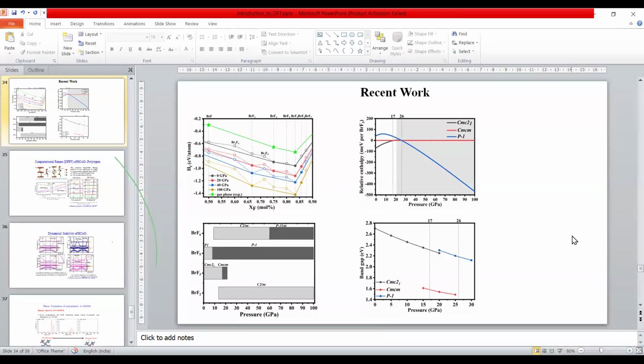If you are using LDA, you find some minus 10 electron volt minimum energy. If you are using GGA, you find minus 12. Then you have to find out which will give you the minimum energy, and a good lattice constant which matches the experimental value. For example, you are talking about MoS2, so you have to find a very good experimental paper which will give you the lattice constant value. Then you compare with your optimized system using LDA, GGA, LDA plus U, GGA plus U, whatever you use. Then you can decide which pseudo potential you have to use. Okay, sir. Thank you, sir.